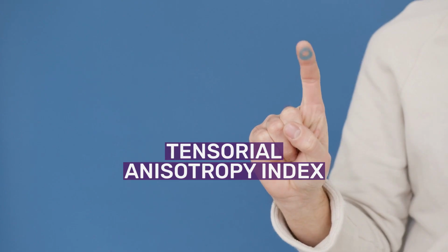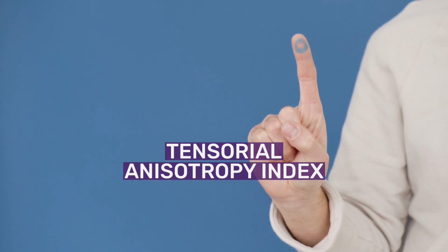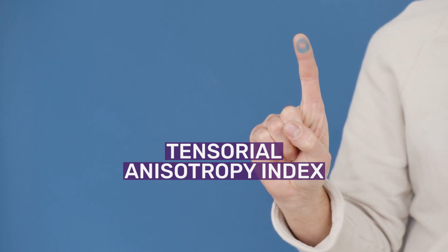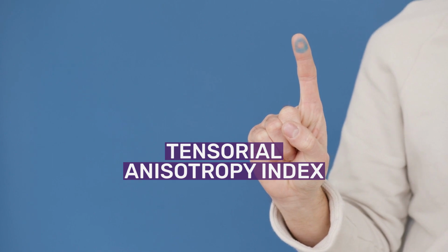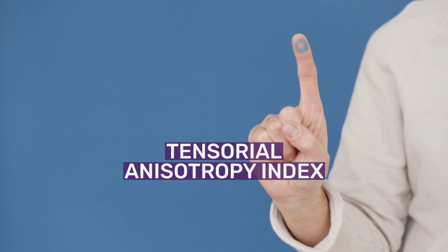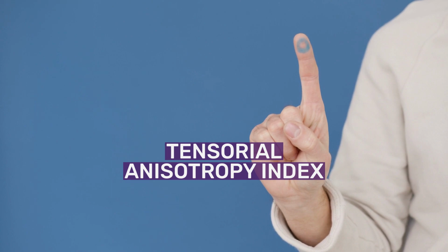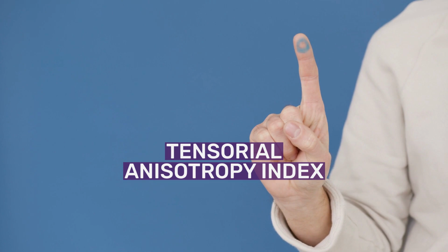Tensorial anisotropy index. The tensorial anisotropy index T extends the Zener ratio for fully anisotropic materials and overcomes the limitation of the universal index, which is designed for materials exhibiting internal symmetries of elastic crystals, which is not always observed in multi-component composites. It takes into consideration all the 21 coefficients of the fully anisotropic stiffness tensor and covers the directional differences among the stiffness tensor groups. It is composed of 2 major parts, the former referring to components existing in the isotropic tensor and the latter in the anisotropic tensor, so that T equals I plus A.